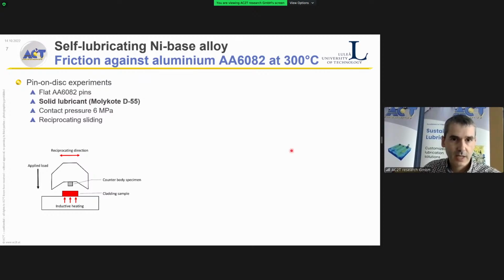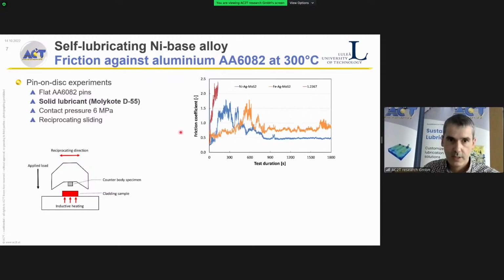Another example, also in this case, model experiments, reciprocating sliding against aluminum alloy. In this case, forming of aluminum is very demanding, so we added some solid lubricant and checked what happens when we have a lubricant starvation. And you can see, for example, a tool steel starts here with very low friction, but as soon as the solid lubricant fails, friction skyrockets and goes over 2, and we need to stop the experiment due to extremely high friction.